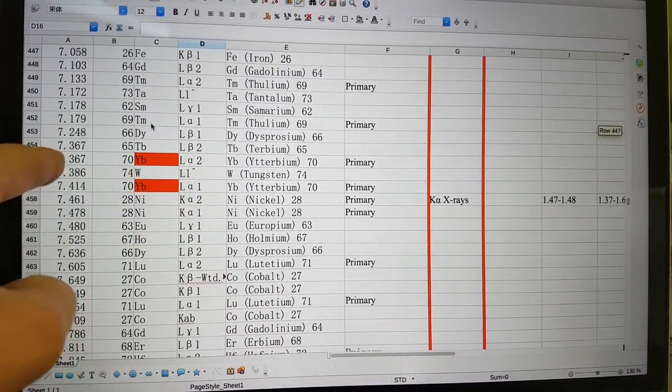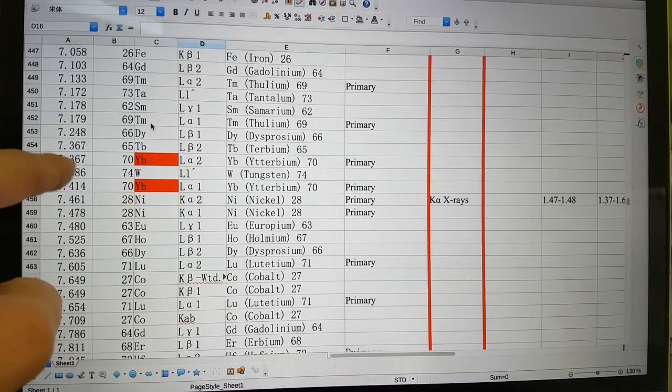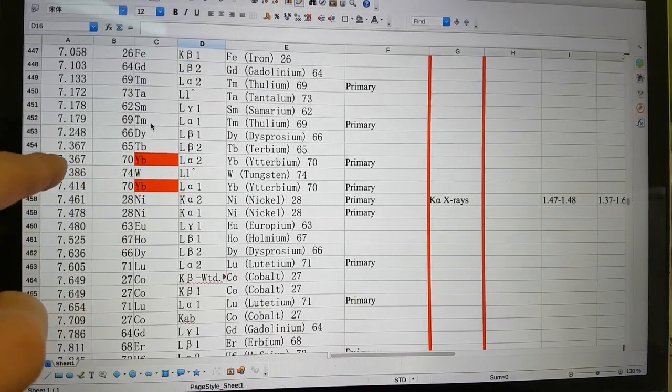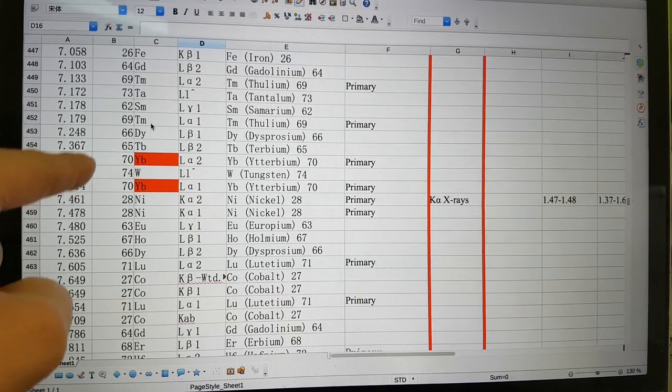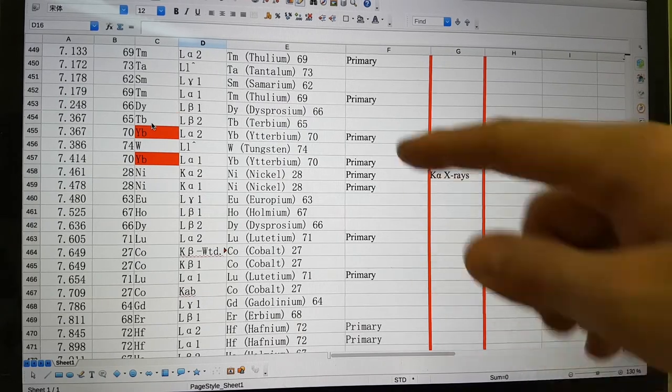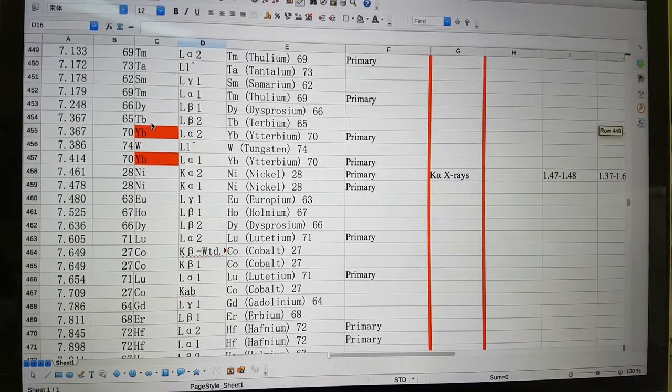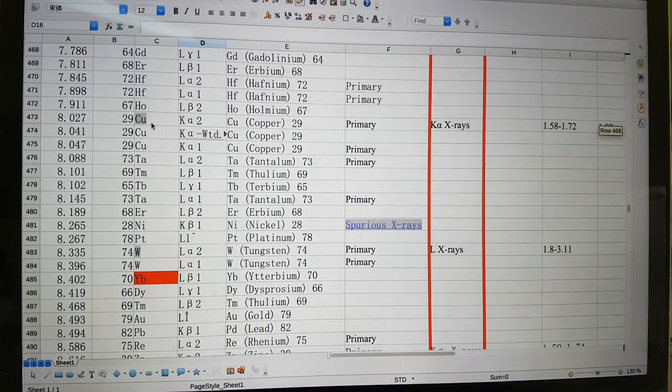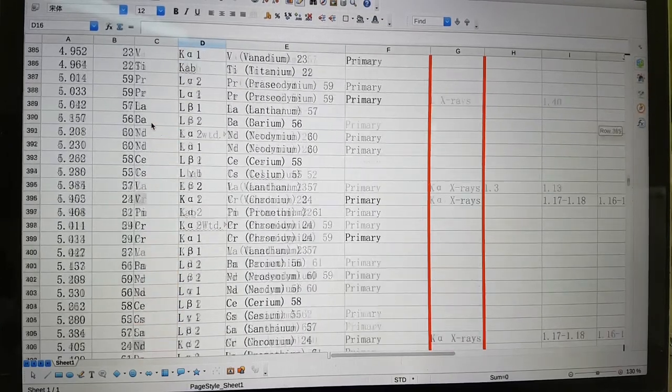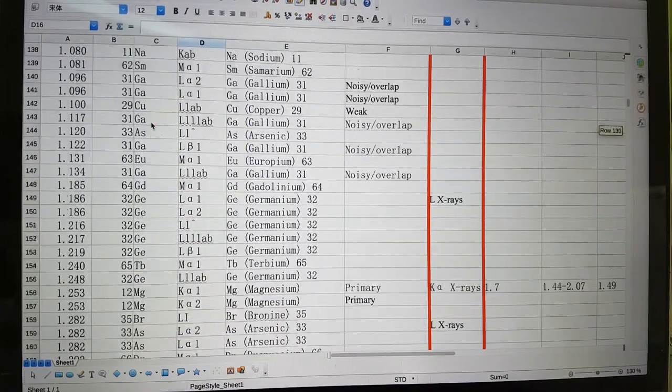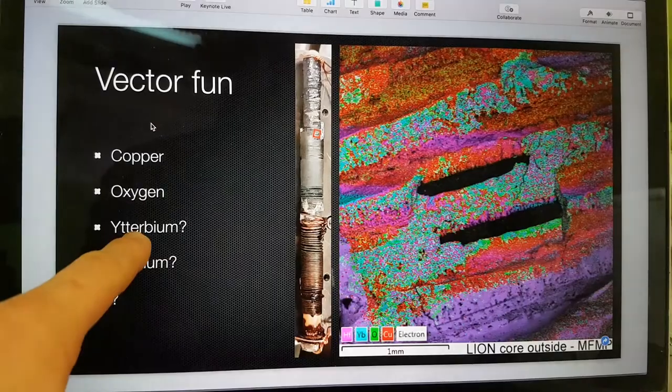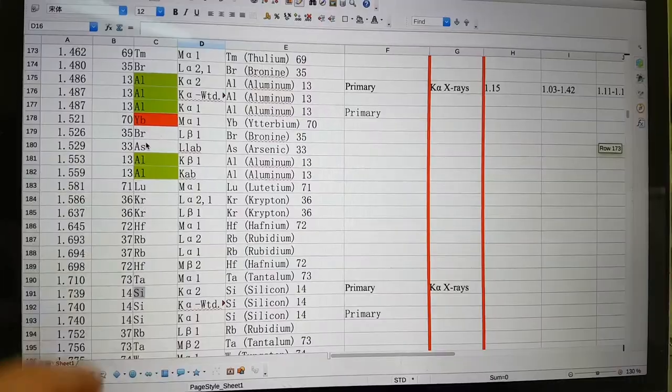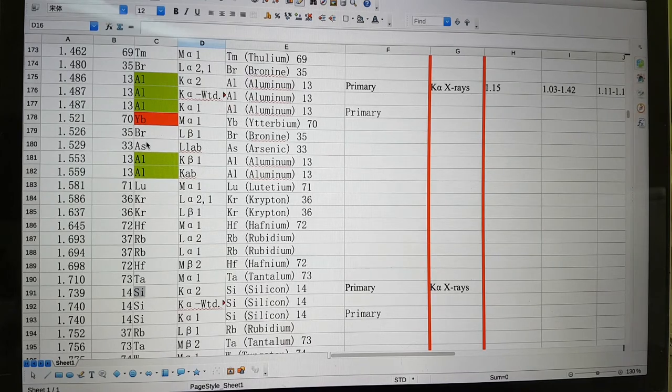So yeah, and up here at these higher energy levels, there's no confusion, so there's no aluminum here. So perhaps we can look at these higher energy levels under EDS, because these are the primary peaks of ytterbium, and be more certain that it is not ytterbium. So for those that think they found ytterbium, and we were not sure, and we were very clear about that when we presented this by putting a question mark there, there is a couple of ways to verify this.